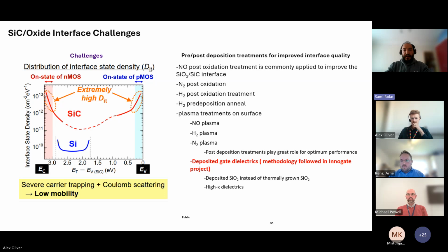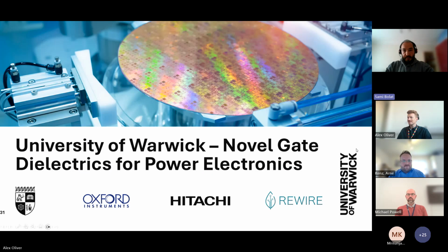And of course, when the interface of the thermal oxide to silicon carbide is this bad, one cannot stop asking himself or herself the question: how about I just deposit the layer and then I stop this oxidation of the interface? And this is the methodology that we follow in the InnoGate project. We basically investigated deposited silicon dioxide instead of thermally grown silicon dioxide, as well as high-k dielectrics. So with that, I will leave the stage to Ben.